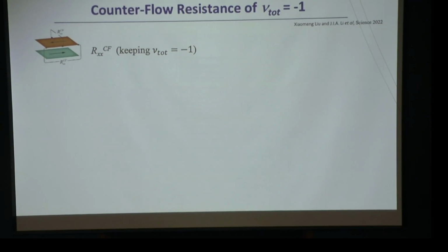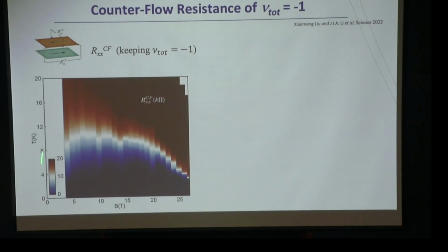And that's kind of what you can see. So we just put this counter-flow geometry, and I can plot how the resistance changes as a function of temperature and magnetic field. And this magnetic field is basically controlling the exciton densities, right? What you see is that this dark blue is basically zero counter-flow resistance, which is condensation, right? As you go up in temperature, it becomes non-condensation. You see that this is a nice phase boundary, which is nothing but how the exciton condensation is changing as a function of temperature and magnetic field.